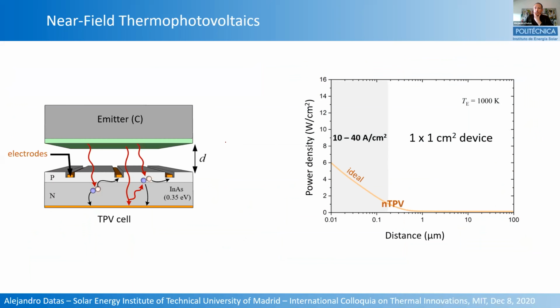Well, if you want to make a near field TPV device at large scale, let's say a 1 by 1 square centimeter device, you will need to incorporate some electrodes in the cell. I have figured out here one possibility, which is to place the electrodes in the front side. Of course, they have to be hidden, let's say, from the emitter in order to be able to create this small distance. So at the end, you have photogeneration, of course, and you have a collection of electrons and holes in these two electrodes.